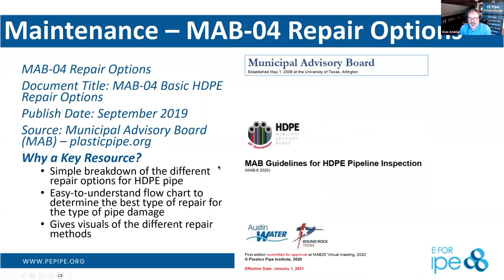So if we didn't do that, Stephen, that area, water main breaks, of course, don't happen at 9 a.m. on a Monday after you've had your coffee. So they're at 2 a.m. and one wants to get that water shut off. We just go back through and put a repair clamp around that at that time, right? Oh, absolutely. Yeah. I mean, that's the thing too. You can just throw a repair clamp on it right then if you want. Any repair clamp that you use on ductile iron or PVC, you can use that repair clamp on polyethylene to stop that leak immediately. And then you can use a squeeze off to cut that piece out later on and then repair it,